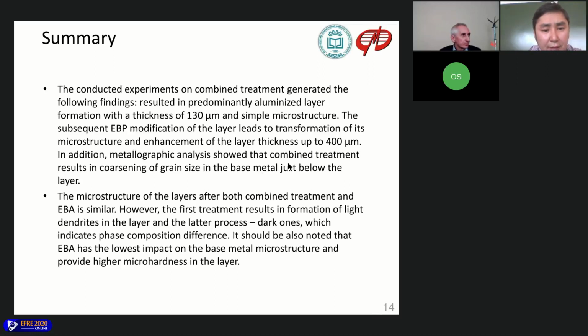The microstructure of the layer after both combined treatment and EBA process is similar. However, the first treatment results in formation of light dendrites in the layer, and the latter process dark ones, which indicate phase composition difference. It should be also noted that EBA process has the lowest impact on the base metal microstructure and provides higher microhardness in the layer.